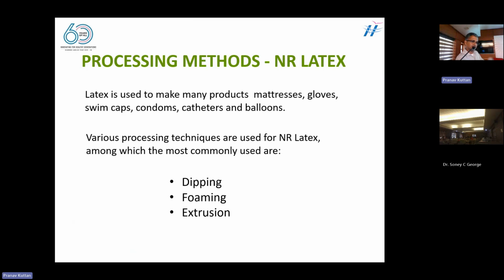Similarly, the seat cover, the bed cushion. This is formed by a process called foaming. Like you are making a cake in your home, some foaming agent is added, and some stabilizer is added, some antioxidants are added. It is subjected to centrifugation. The foam will come out. This can be poured on a mold. Then the bubbles will come out. The foam material comes out. So it will form pores. It will form vessel channels, which will give a foaming material. This is how the foams are formed.